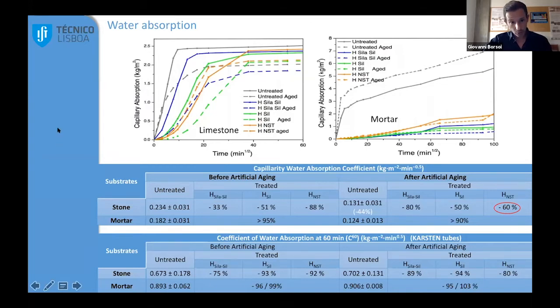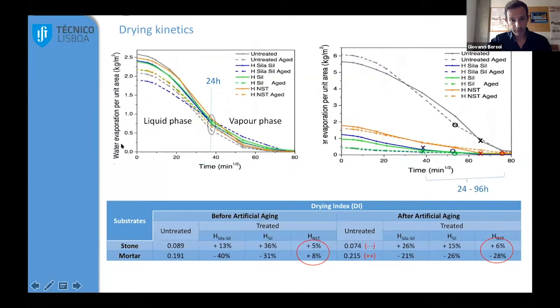When we look at the drying kinetics, we can see that in the case of the limestone, in all the cases the liquid phase evaporation, so the first step of drying, ends after 1 day. So in all the cases, after 24 hours, there is basically an inversion of the drying process to the vapor phase.